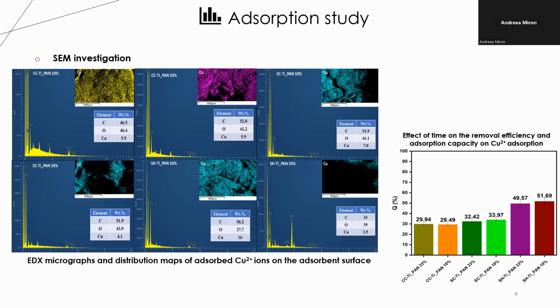And the range is from 29.5% to 51.6%. Thus, for the commercial chitosan beads, the removal efficiency is similar for both filler percentages, approximately 30%. For the beads obtained from chitosan from commercial chitin, the percentage is approximately 33. And for the beads with chitosan from shrimp shell waste, we have a percentage around 50.